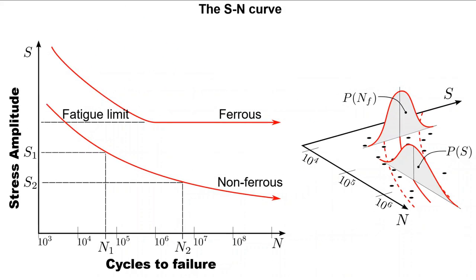Each of these SN curves aren't derived by a single set of tests, but are captured by numerous specimens. As we've seen from Weibull's theory, there are some material conditions which are stochastic, that is, ruled by chance and probability. For any material system, there is a chance that the microstructure will fail at a higher or lower stress for a given number of cycles and vice versa. So, the SN curve is viewed as a representation of a probability density function, either for the stress or numbers of cycles that can be withstood before failure.